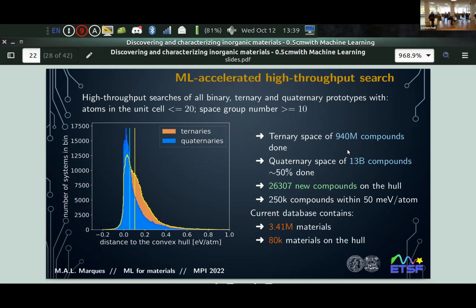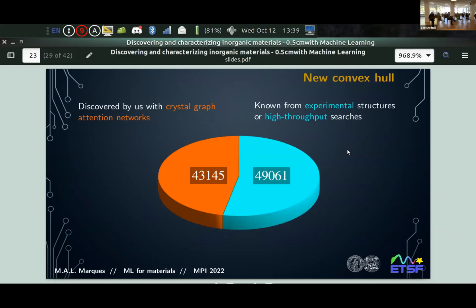So these are all compounds that we have some hope, or let's say the probability of being able to synthesize them is relatively large. Our current database is 3.4 million compounds, so we did an extra million calculations, and we have 80,000 materials in total that are thermodynamically stable. Just to put this into perspective, the orange slice was before we started. So our hull had 43,000 compounds. These are the thermodynamically stable compounds, and part of this are already predictions from our group from before. And we found another 49,000. So we essentially doubled our knowledge of stable inorganic compounds in the last year or so.